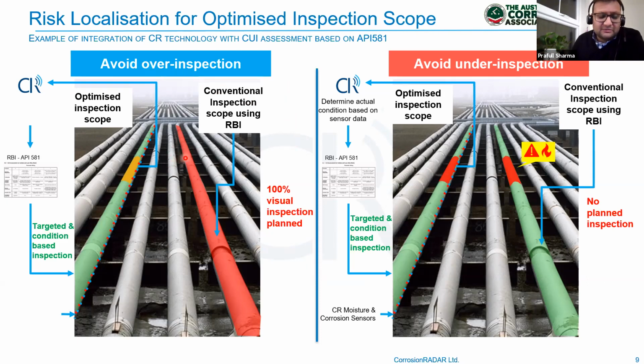There are two pipes here, with a similar profile, but one of the pipes, shown in red color, is very high in risk. Red means very high. So the conventional inspection scoping using RBI will very likely say that this needs to be 100% visual inspection. Visual inspection means you have to remove the insulation. It's expensive. But then if we combine it with monitoring, say in this case the sensors are installed and they are saying that, yes, RBI is saying red, but the sensors are saying these are green conditions. There's no water or humid condition inside, but there's a slight issue somewhere in the middle. It's a medium type risk using API 581. Now, if we combine both pieces of information, then we can optimize the inspection: we need not inspect all of it. We just need to inspect probably that 1 meter. So that will avoid over inspection.